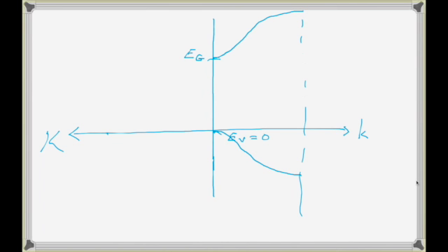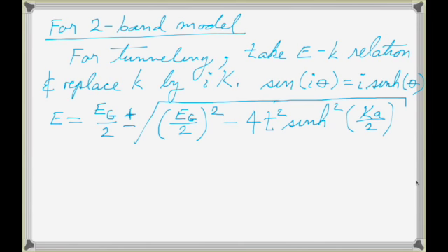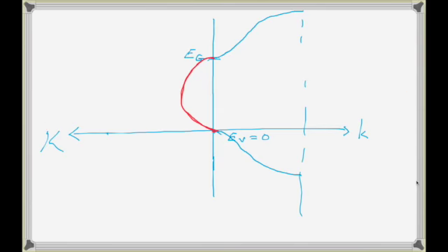And now in the band gap, this is what you're going to have. So it wraps. This thing wraps smoothly between the conduction and valence band edge. So if you go back and you were to plot this function, you would see it would wrap smoothly around. When κ is 0, it's just the two band edges, and then you just have to go through it and plot it.